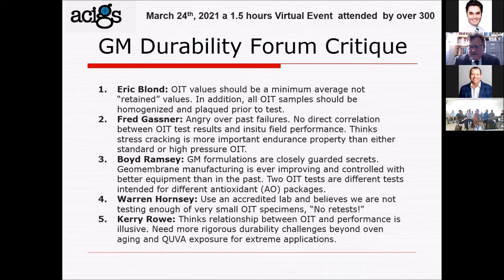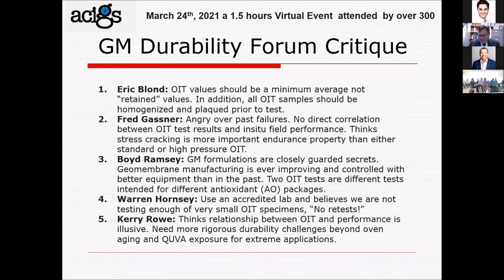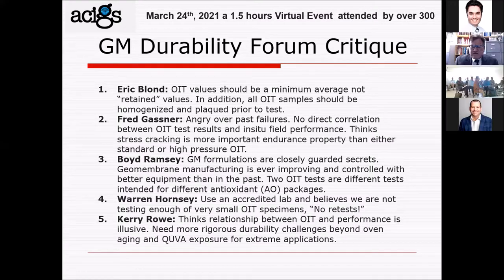The forum was very nice — five speakers, all very well known. Eric Blond, now a consultant, worked for a huge geosynthetic laboratory, SAGEOS in Canada, and then for Solmax. Eric would like to have the OIT values in GRI GM13 as minimum average values rather than retained values, with all material homogenized in plaque before running the test to reduce variability. He presented data showing the coefficient of variation for the two tests: standard OIT is in the single digits and high pressure OIT is in the double digits. He thinks both can be tightened with some sample preparation.